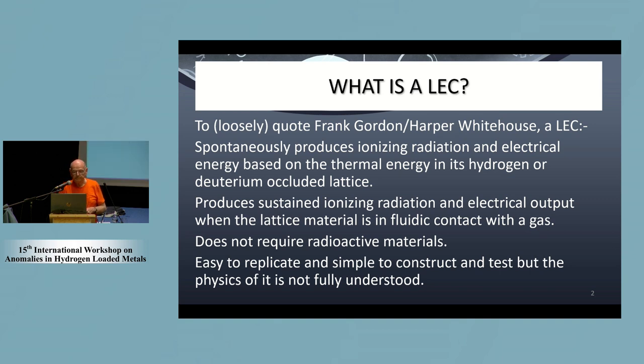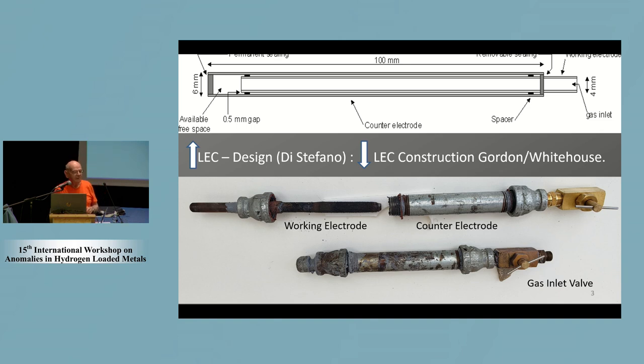So, here we go. This is the kind of design that Frank and Antonio Di Stefano in particular have been using. I think John Paul has been using similar, though on a different scale, electrodes. In the inside there, you see the working electrode in the dismantled one at the top, and the counter electrode, which, as you can see, is a plumbing fitting. So that's the basic geometry that they were using. I've been doing my work with flat plate electrodes in air, because there is no necessity to use hydrogen, but we'll get to that in a moment.